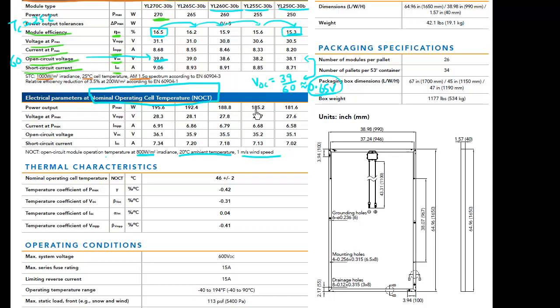So the cell will essentially rise up in temperature. Typically for these crystalline silicon based cells, it can vary all the way from the cell temperature for this particular ambient condition and this irradiance. It can vary all the way from 40 degrees C to all the way up to 70 degrees C, depending upon how good is your module design to carry away this heat. And also it depends upon what is your irradiance level as well.